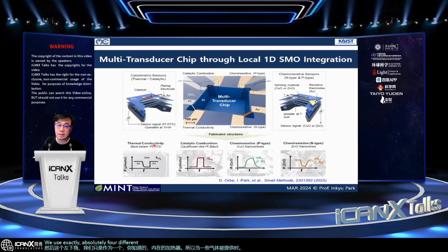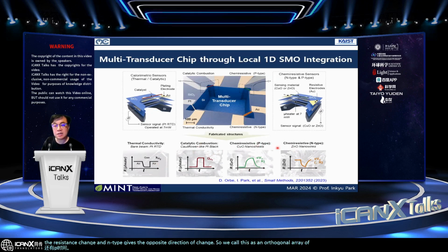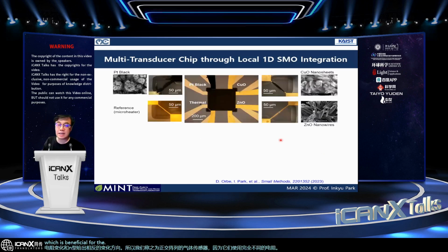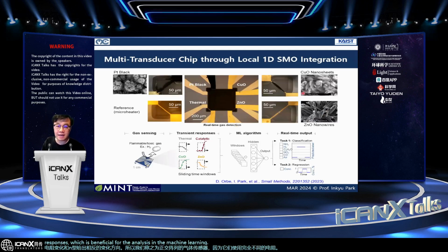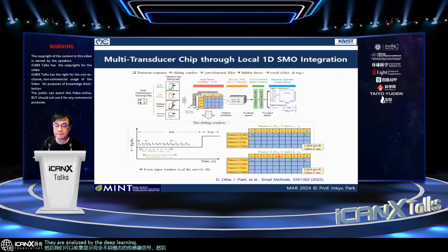four different sensors. The first one, we measure the thermal conductivity. This one we use for the catalytic combustion property of gas. And the p-type gives the resistance change, and n-type gives the opposite direction of change. So we call this an orthogonal array of gas sensors because they use completely different responses, which is beneficial for the analysis in machine learning. So this is a fabricated device that when some gas is given, we can collect the sensor signal, which shows quite different modality, and then they are analyzed by the deep learning method.